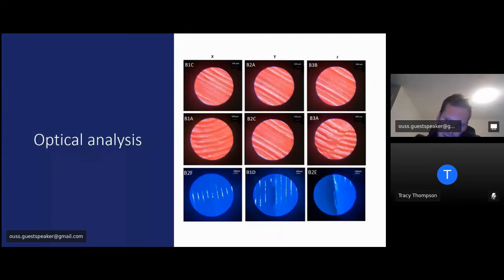And what that's doing is that's stretching out the fibers. So the bottom picture there, you can see B1D. So you can see a stretch, and it's pulling the fibers apart, which is actually reducing some of the tensile and compressive stress on that part, and also some evidence of brittleness as well.